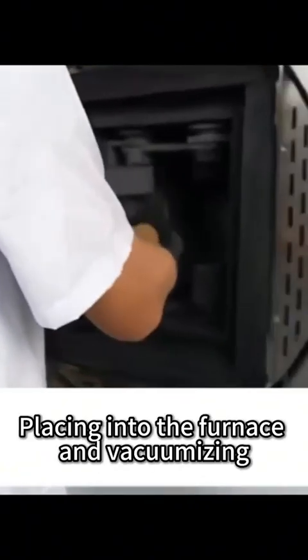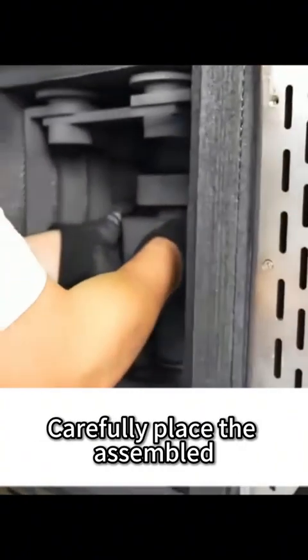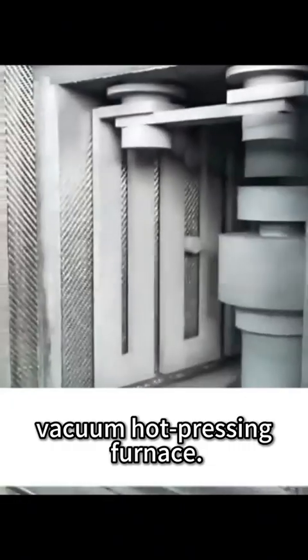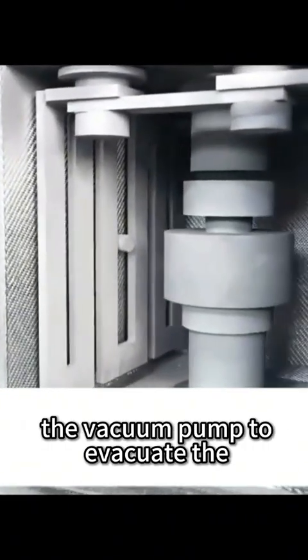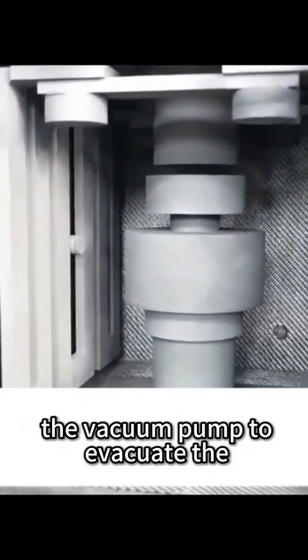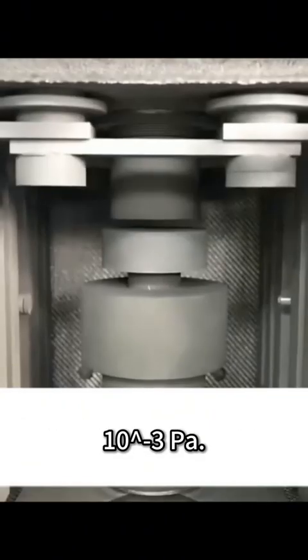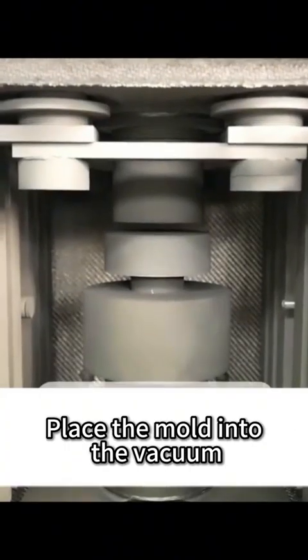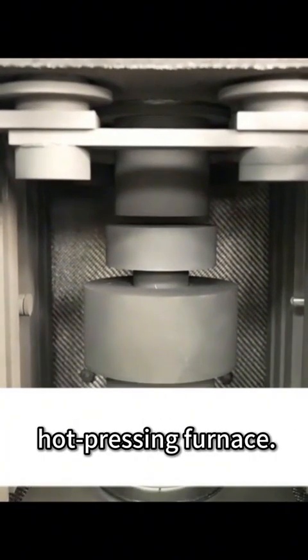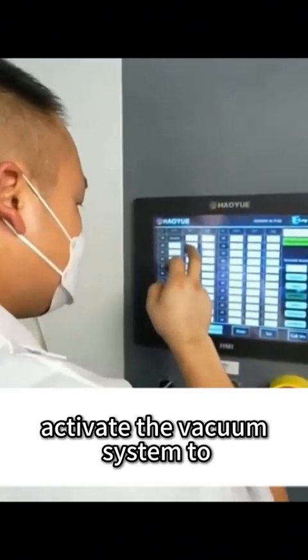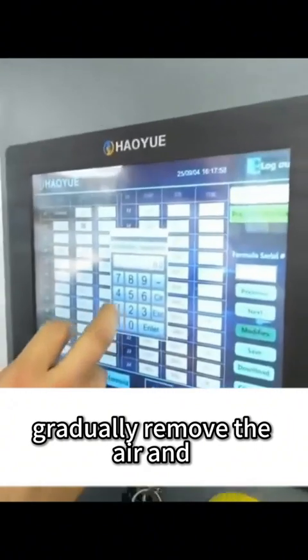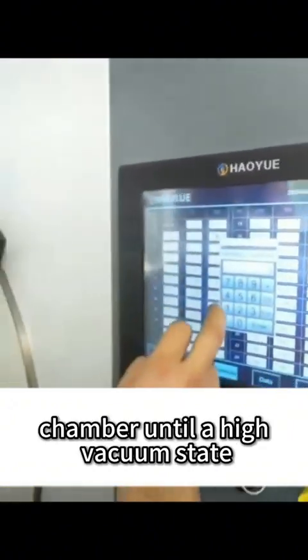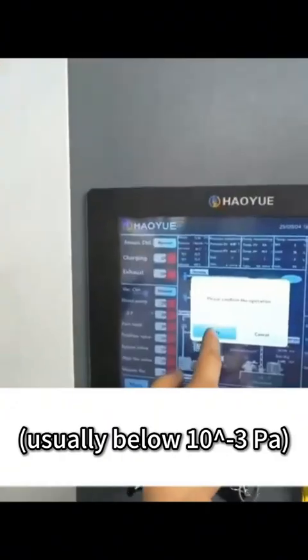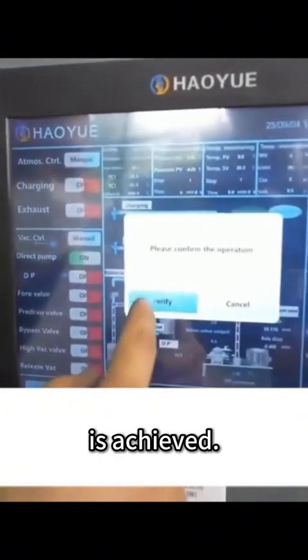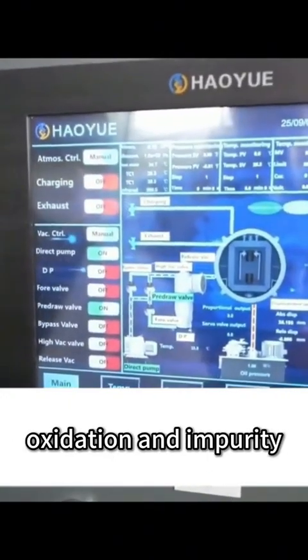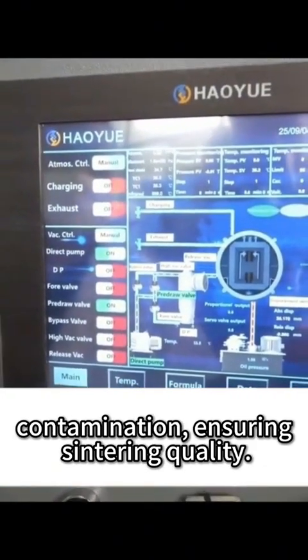Placing into the furnace and vacuumizing. Carefully place the assembled mold into the chamber of the vacuum hot pressing furnace. Close the furnace door and start the vacuum pump to evacuate the chamber to approximately 10^-3 Pa. Monitor the vacuum gauge. After closing the furnace door, activate the vacuum system to gradually remove the air and moisture inside the furnace chamber until a high vacuum state, usually below 10^-3 Pa, is achieved. The vacuum environment prevents oxidation and impurity contamination, ensuring sintering quality.